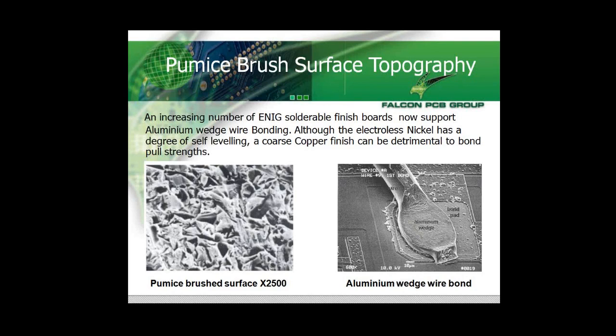Electroless nickel tends to have a self-leveling effect during its plating of the 5 microns that we would normally plate on the surface. But if you get the copper surface too coarse, especially if you're doing the same process for all surface finishes, i.e. if you use things like immersion silver, then you do not want a coarse copper surface prior to applying immersion silver, or you will get solderability issues. Aluminium wedge wire bonding, of course, benefits from a very good smooth surface to get the best pull strengths.